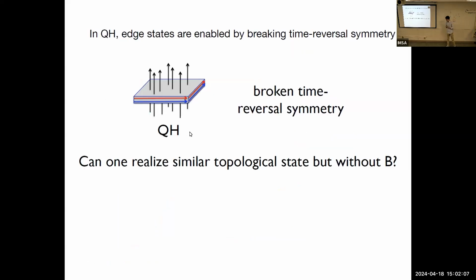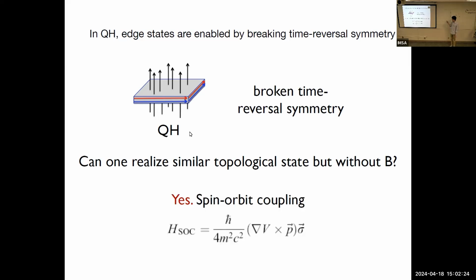So this 2D electron gas system, you can realize this quantum Hall effect only if you apply a magnetic field and break time reversal symmetry. And people then started thinking, can one actually break it without applying a magnetic field, say with spin orbit coupling? And it turned out it's possible. You can make systems which have high spin orbit coupling, and then you will have these topological edge states as in the case of the 2D electron gas, but without a magnetic field.